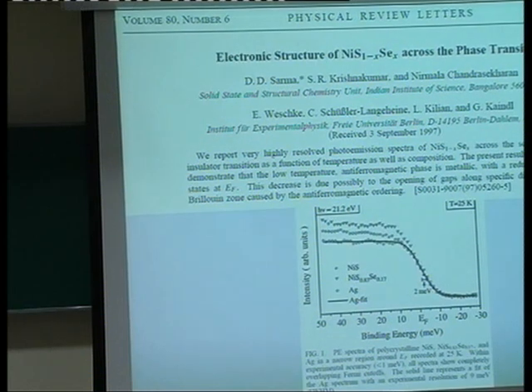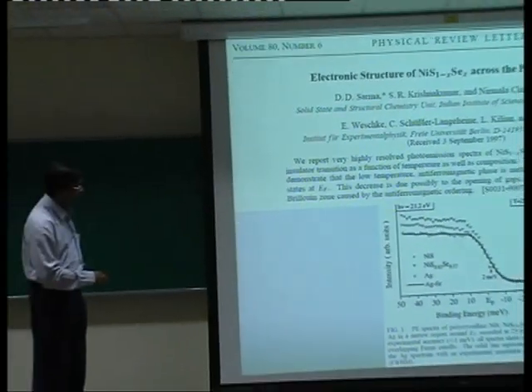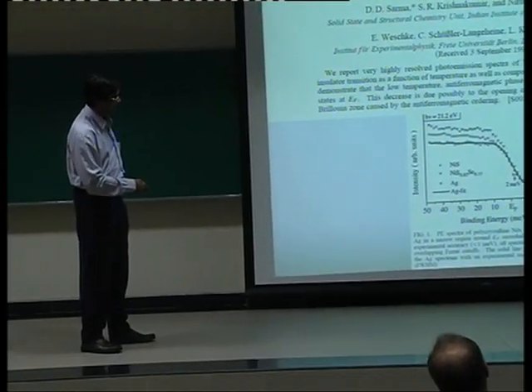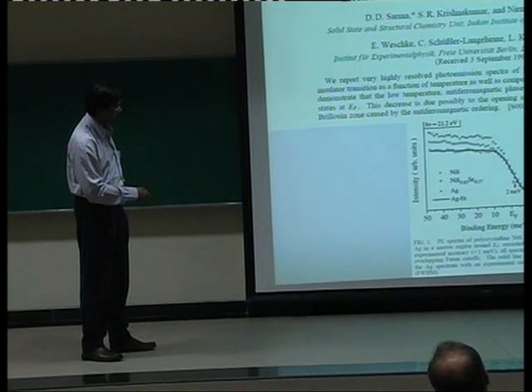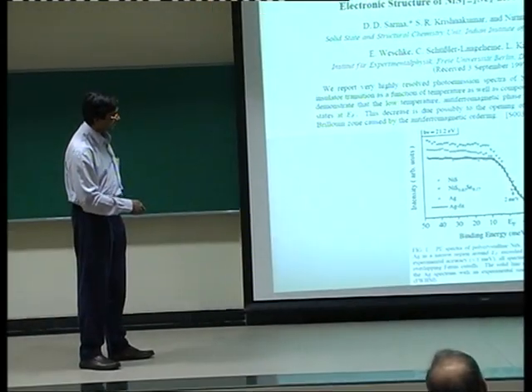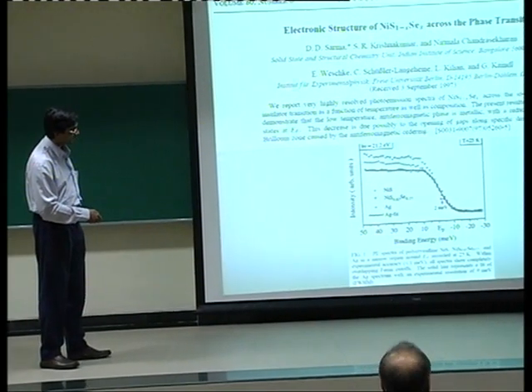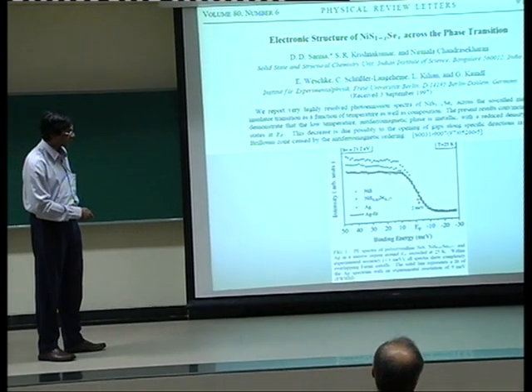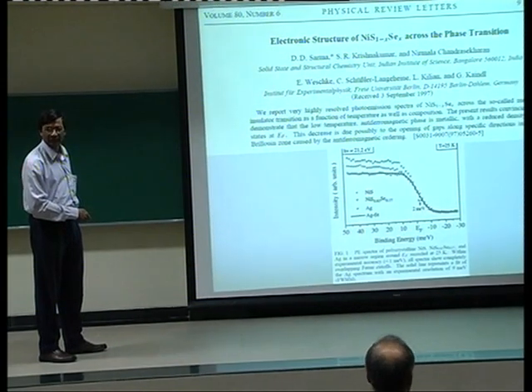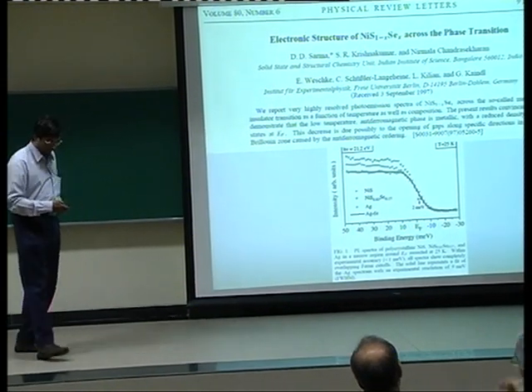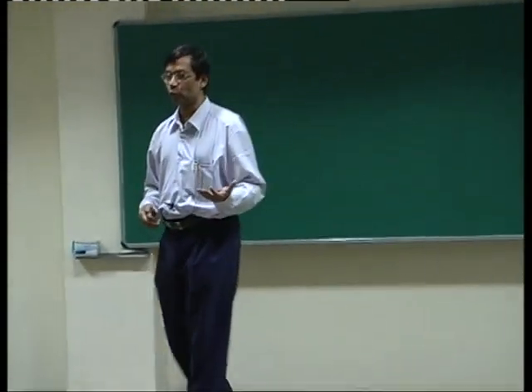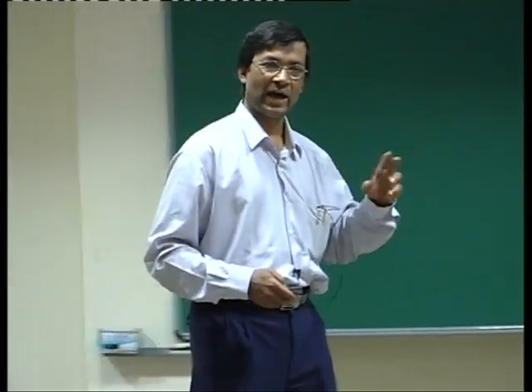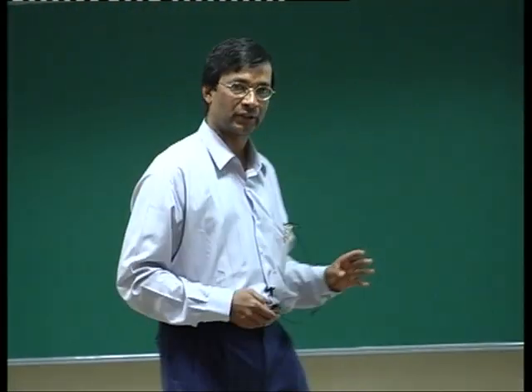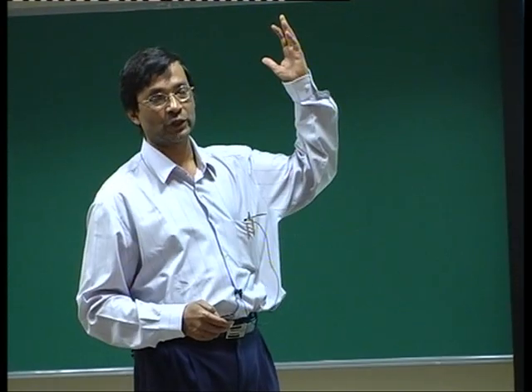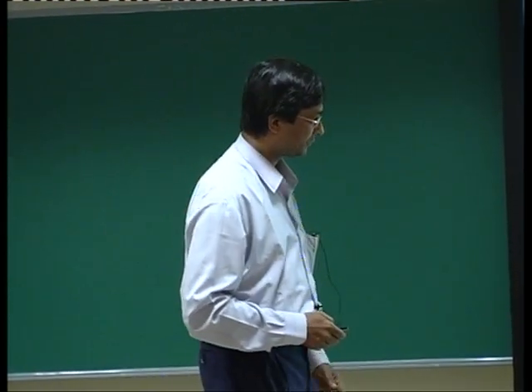Okay? So basically this one, which is between the well-known metal silver and the well-known metal here of the same crystal structure, suggests that there is no large gap. If there would be a gap of 2 millivolts, we'd be able to see that very clearly. And there is no gap. If there is a gap, that has to be lower than 2 millivolts, which would be consistent with the fact that the temperature coefficient of resistivity does not give us an exponential upturn down to 4 Kelvin.